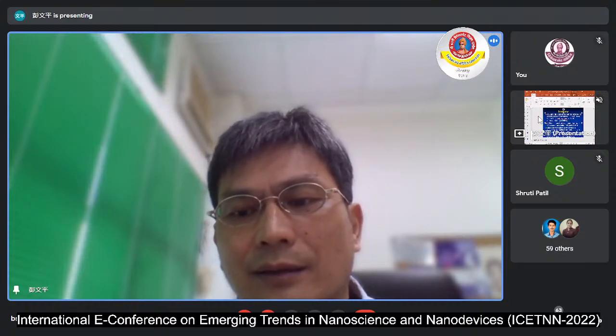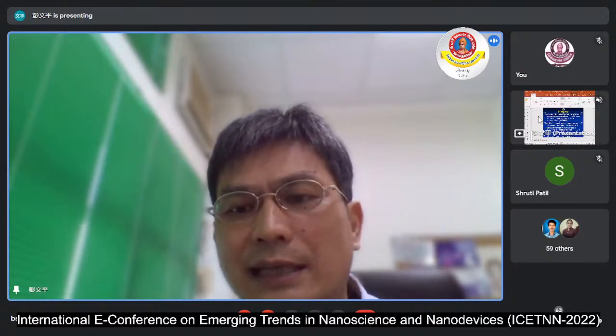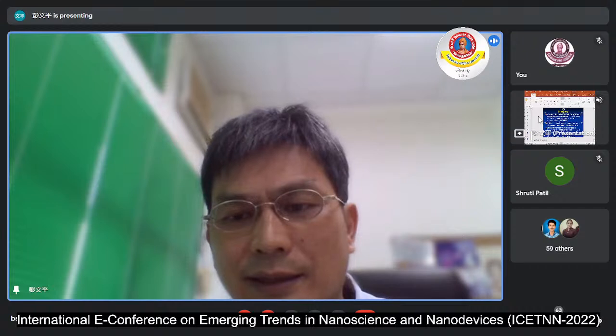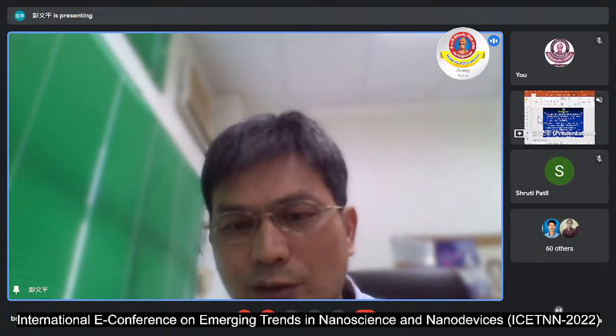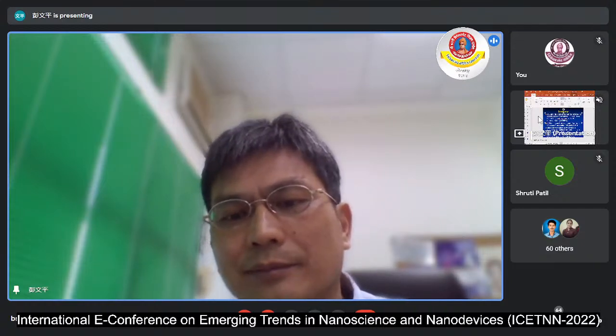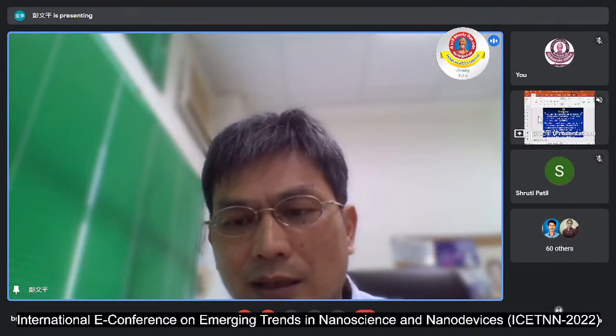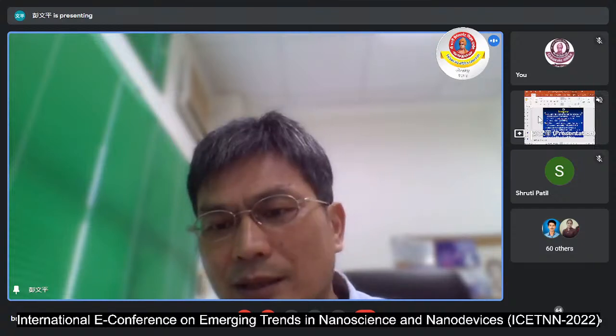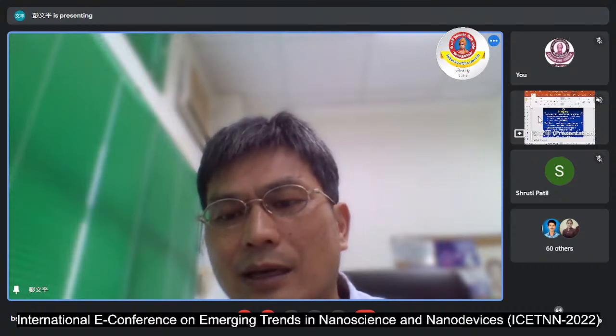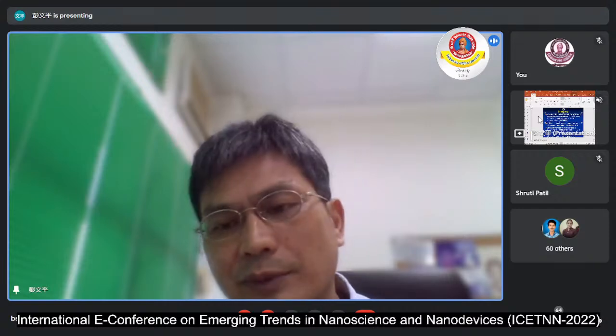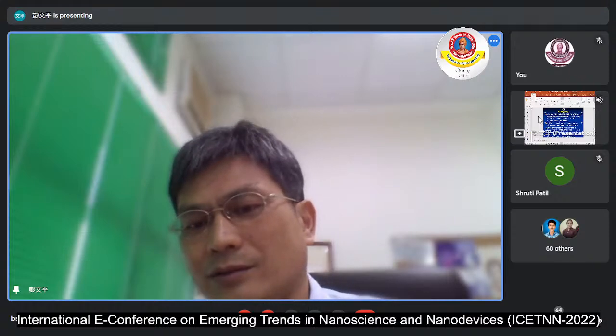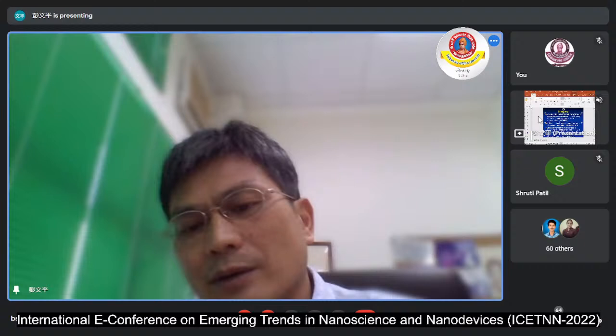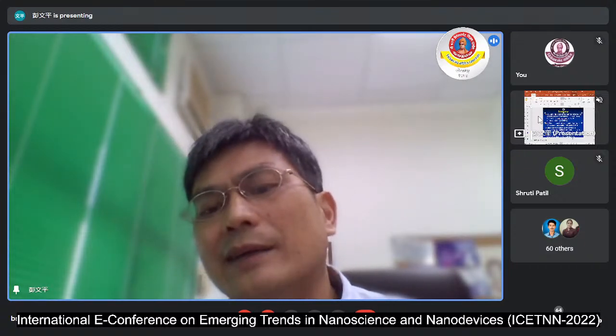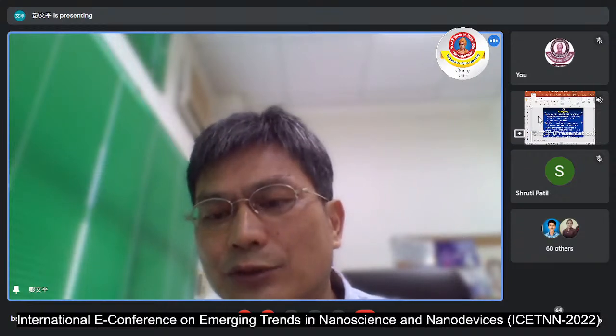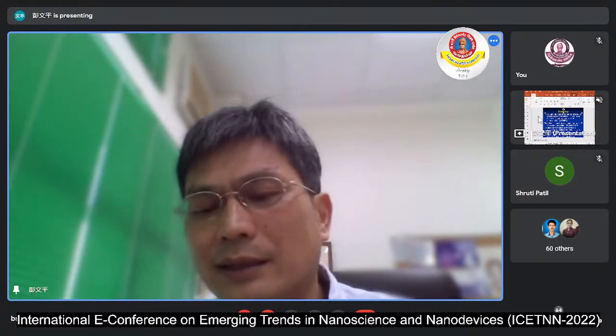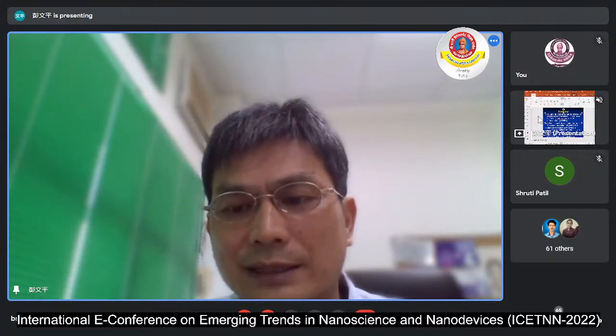I can summarize what we have found. Here we can detect IgG and IgM antibodies at a 5 nanomolar concentration using the nanodiamond. Okay, this is our observation and our measurement. And the IgM mass spectrum we can acquire for the first time using a linear ion trap system. This is found for the first time in the world. And also we can do direct quantification of antibody using nanodiamond with mass spectrometry technique for detection. So that means direct quantification, okay, not indirect. You have to be careful about this. This is direct quantification without sample preparation, without dye labeling. We can do it directly. Finally, the orientation of the antibody is confirmed. It is most probably the tail-on configuration. This is also the first time we confirm this.